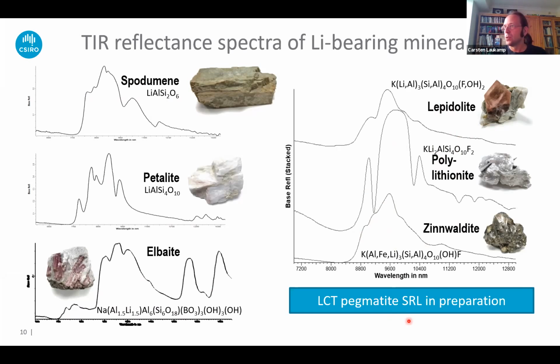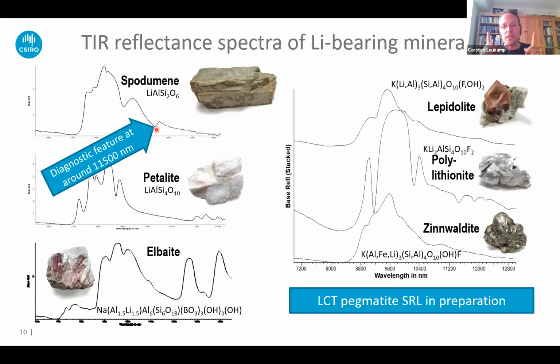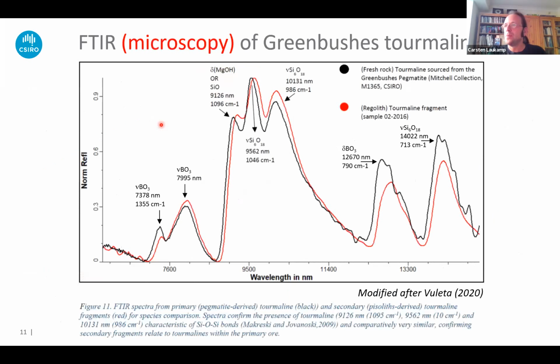Monica is looking after that, Monica Legrand. I might point out here this feature around 11,500 nanometers, which is not an absorption feature because we are actually in the thermal infrared. In the thermal infrared, the peaks are the absorption features, and the troughs are not the absorption features. They are not related to any molecules. That's basically what's left over in the spectrum. But this feature is quite useful for tracking the spodumene content, and we're going to look at that later on in a bit more detail.